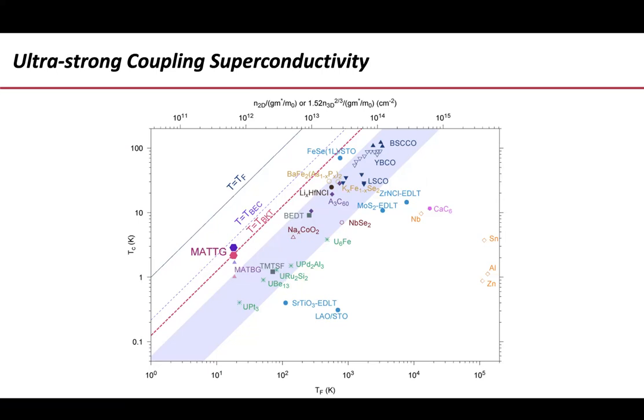In this type of plot, conventional weak coupling BCS superconductors tend to be near this corner. For example, aluminum has a TC of about one Kelvin with a gigantic density of electrons, a gigantic Fermi temperature of over 100,000 Kelvin, okay? The more you go in this direction, the more exotic your superconductor is, okay? And in particular, in this purple band, you have all the superconductors that people suspect are unconventional, okay? You have the cuprates, you have the pnictides, you have the heavy fermions, you have the organics, et cetera, okay?